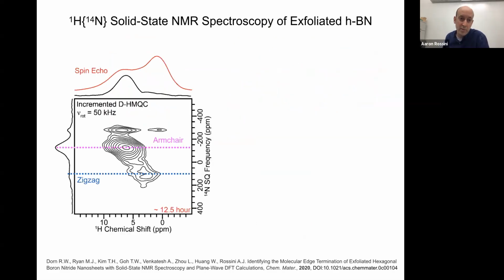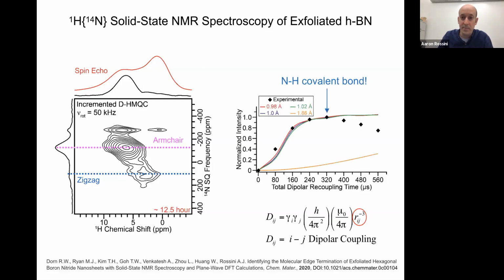We also went one step further and did nitrogen 14 NMR. We did this using room temperature, fast magic angle spinning experiments. So this is a proton detected nitrogen 14 DHMQC spectrum, dipolar HMQC. This is using techniques that were developed by Zhehong Gan, Geoffrey Bodenhausen, Jean-Paul Amoureux, and some of those people. In this spectrum, we could get this in about 13 hours, and we can see two nitrogen NMR signals. I'll talk about those more in a second.